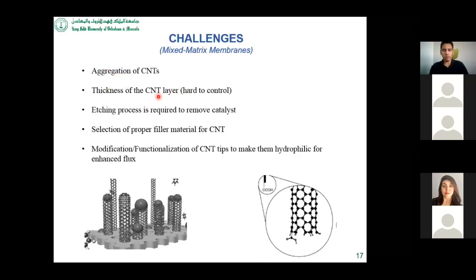Then if you are adding the carbon nanotube into the polymeric membrane, remember all this is happening at a nanometer level. So how can you control the thickness of the layer? Because again, you need to define an optimum layer thickness. If it is very low or if it is very thick, then of course the property will be disturbed. So this is another challenge. You might develop some modification techniques of the polymeric membrane where you can add CNT with controlled thickness.